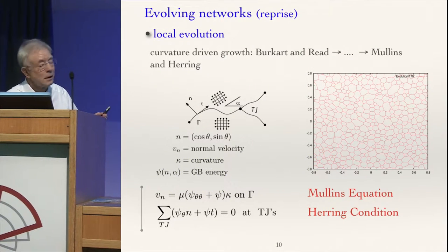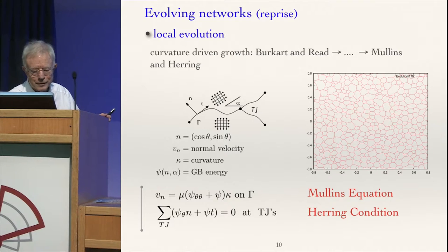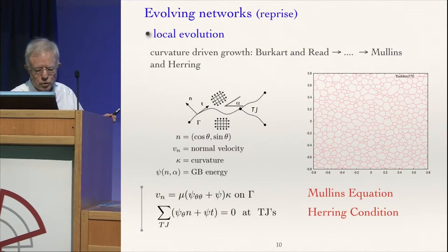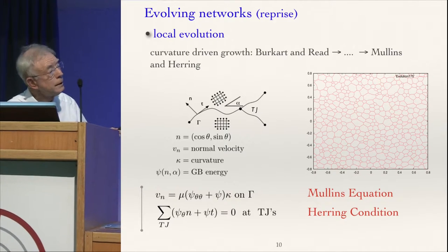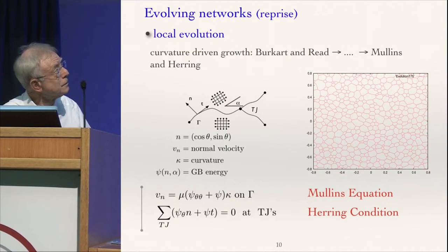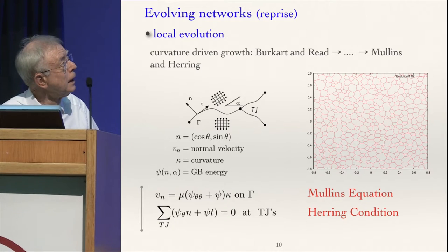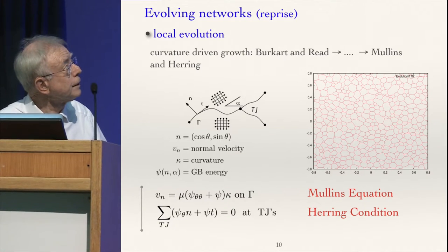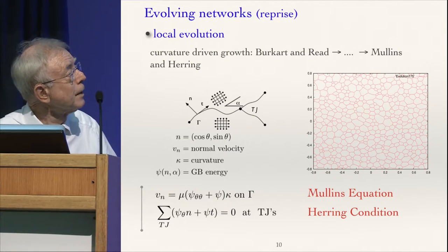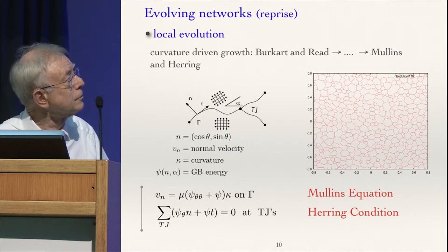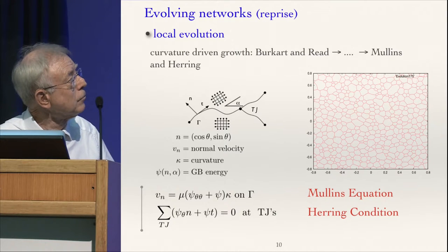Okay, so here is our reprise of what an evolving network means. Curvature-driven growth began perhaps with Burkhardt and Reed. This particular version is due essentially to Mullins. It's just what you think. There's a normal vector and a tangent vector. There's a lattice and a lattice misorientation. The curve moves by its normal velocity according to curvature and a grain boundary energy density. And the normal velocity is some kinetic constant times psi_theta theta plus psi times kappa on the curve.